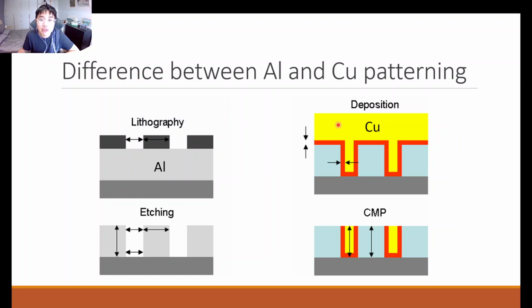So there's a difference between aluminum and copper patterning schemes. When we shift from an aluminum-based interconnect system to a copper-based interconnect system, there's a difference in the way that we have to pattern these metal features. Let's take a look at the left-hand side. Let's assume this is aluminum. For aluminum patterning, we can deposit a uniform layer of aluminum, for example, through evaporation. After that, we use lithography and subsequently plasma etching to define the shape and the location of your aluminum features.